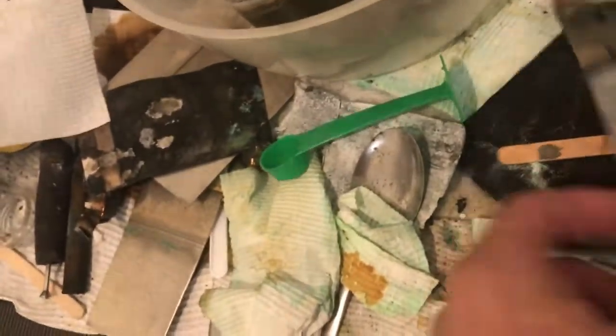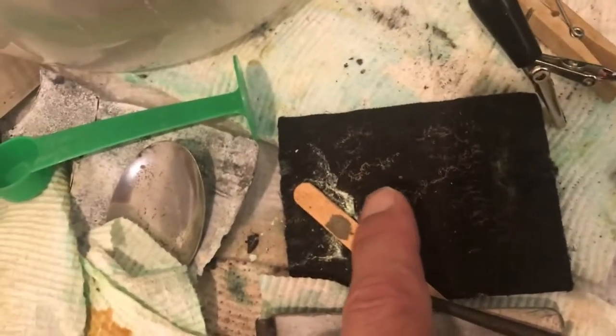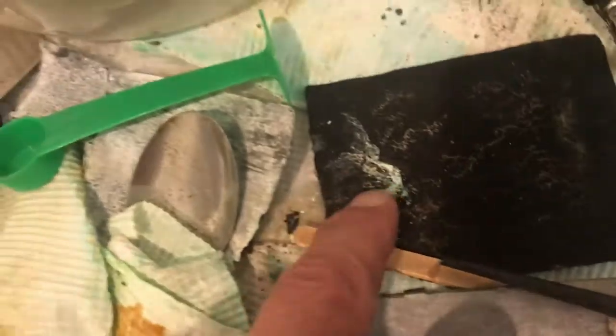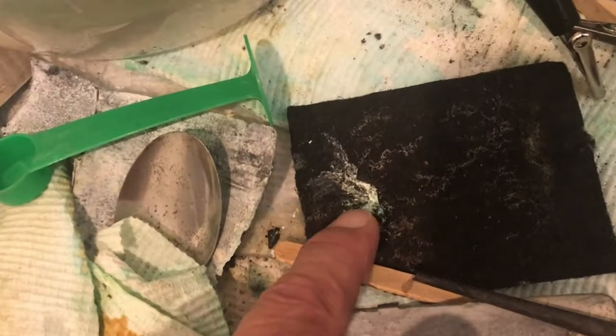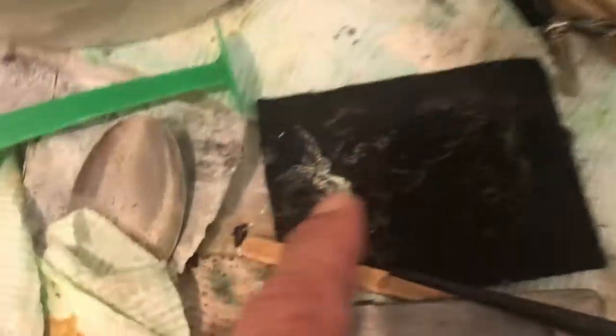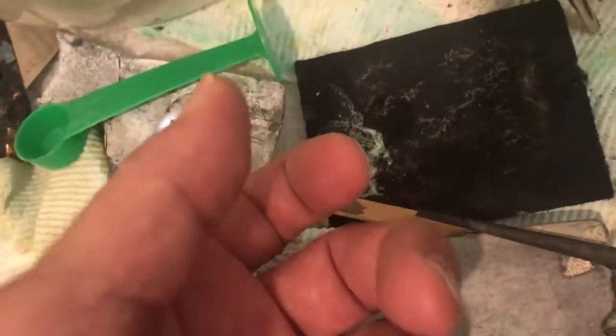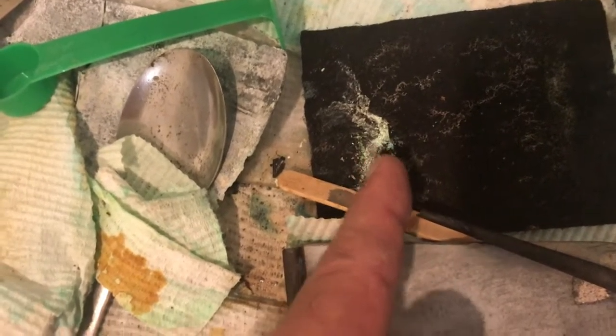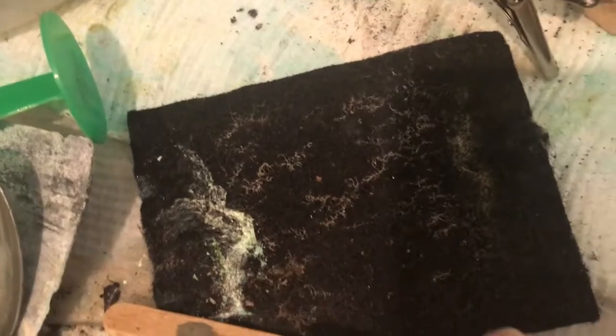You have to leave it out of the liquid. See, it forms those bubbles. If you don't copper plate it, this one here, now that's had 40 hours. That was just the conductive ink and straight into the nickel. And it started forming this maybe nickel oxide. I don't think it's nickel oxyhydroxide, but it does sink down to the bottom, this white greenish material. It reacts at the boundary layer of the electrolyte with oxygen. So that's why I think it might be nickel oxide. And it forms rapidly and produces a fair bit. So that was 40 hours and all you can see is a few traces of nickel plating. That's why it's better to copper plate it first.